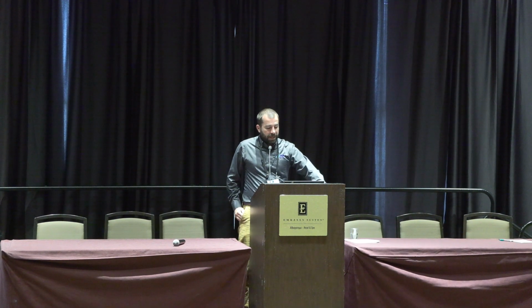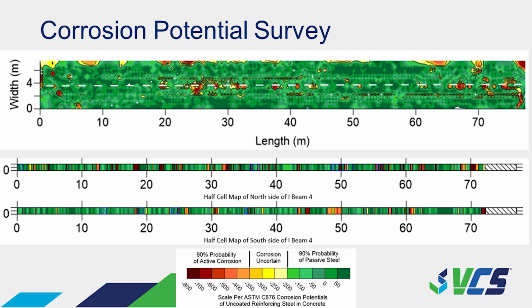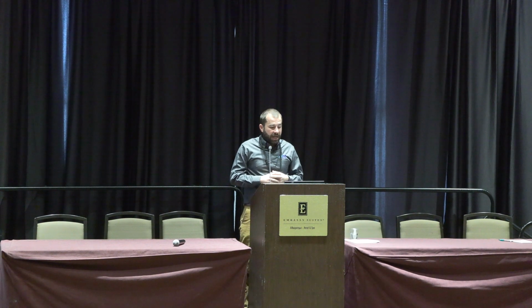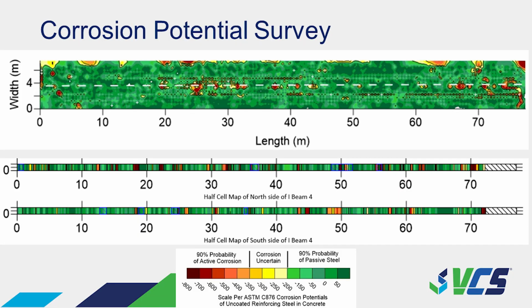So the first step is a corrosion potential survey, understanding where the active corrosion is and the risk for corrosion in the structure. Here you see the top one is the bridge deck, so we surveyed the bridge deck. And the underside is the survey along either side of the beam, looking at the actual corrosion activity of the top of that beam embedded in the concrete. What we're seeing here is actually not a terrible lot of corrosion. The hot colors, the reds, yellows and oranges, are where your active corrosion is going to be. On the top deck there are some areas of active corrosion, but it's not terribly bad just yet.